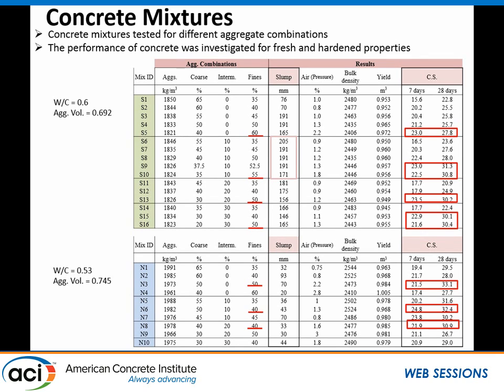What you see here is interesting. You get the highest packing and highest compressive strength at 60% fine for binary, 50% fine at ternary with 10%, 50% fine at 20, and then 50% at 30. So these are the maximums happening here. You get 27 for binary, but if you replace 10% of your coarse aggregate with intermediate, you get 31 to 30 compressive strength.